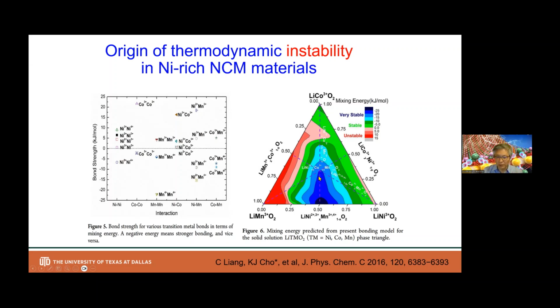So if you have 3 moles of material, this material is 20 kilojoule per mole more stable than as a compound of mixing this cobalt, nickel, manganese in the metal oxide layer rather than having three separate phases. So that's what this phase diagram represents. But as you can note, lithium manganese oxide is not very stable because manganese's favorable oxidation state is 4 plus. Lithium nickel oxide is marginally stable.